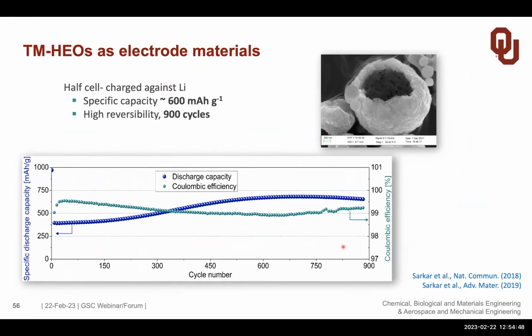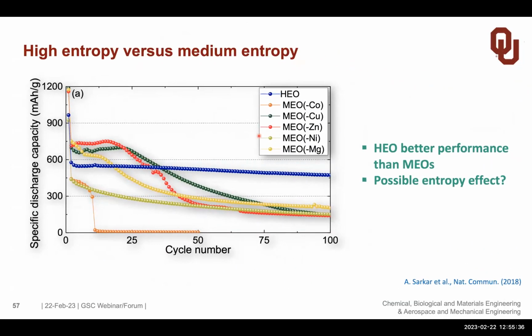So that makes it interesting, in particular, if you have high capacity and good cycling stability, which we have found. And the capacity is substantially better than in existing materials. So we have gotten up to 600 milliampere hour per gram. This is showing that we can have good reversibility up to 900 cycles. Still, this is far away from being applied as a battery material in technological applications, but we have worked closely together with a company in Germany, BASF, which is a large chemical corporation, and they have started to interact with us on that field.